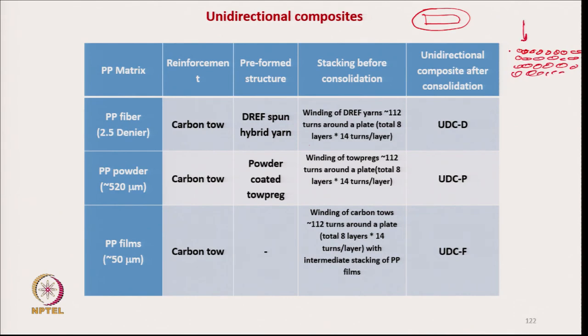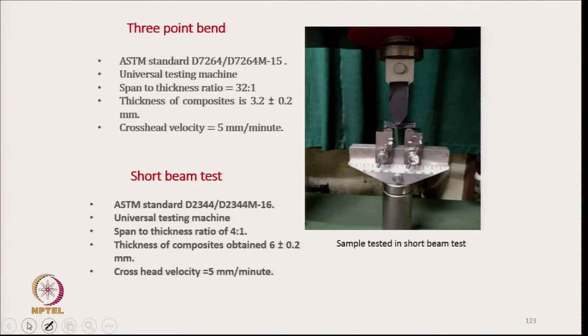The total material is put under the compression molding, and we get the compression molded composite. As it is made from DREF yarn, it is called UDCD. Similarly, for carbon tow powder, 8 layers and 14 turns, it is UDC, the unidirectional composite made from powder coating. For PP film, a 50 micron thick film with carbon tow, again 8 layers of 14 turns, but with films in between. This is UDCF.